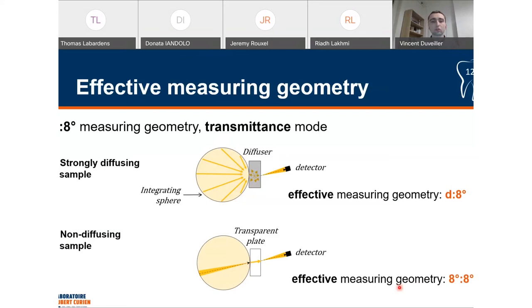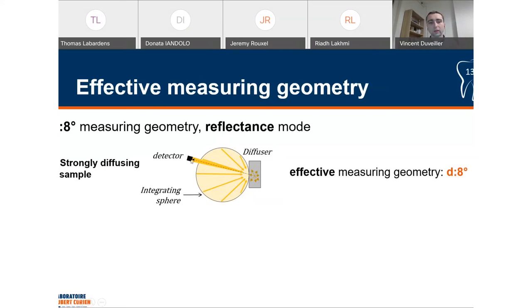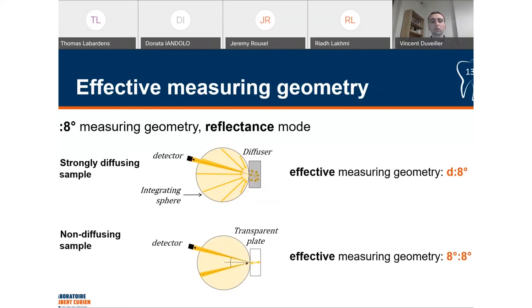Now in reflectance mode, it's basically the same. When in the first case we measure the reflectance factor of a strong diffuser, the detector collects the radiance from the whole integrating sphere, so the effective measuring geometry is hemispherical directional. But if we measure the reflectance factor of a transparent plate or a mirror, for example, the detector only collects the radiance from one direction, so the effective measuring geometry is bidirectional. So this means that the effective measuring geometry depends on the type of material that you are measuring.